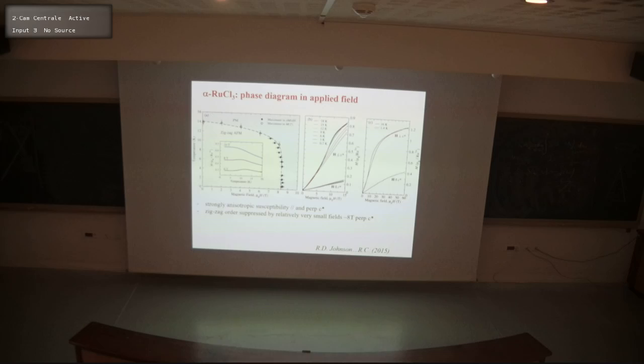So here I'm showing measurements done of the phase diagram in applied field. There's very strong anisotropy between field applied in the plane and orthogonal to the plane. So here are measurements that we've done on a stack of ruthenium chloride sheets to observe that there's a suppression of the magnetic order visible via an anomaly in susceptibility around about 8 Tesla, and there's no further anomaly above that. And here magnetization measurements to indicate again this anomaly, which goes away at high temperatures.